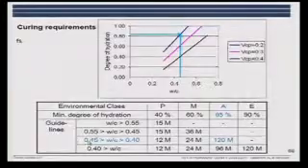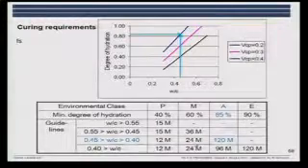And if we look at this table here and take an example where it's a concrete to go into an aggressive environment, and we have a water-cement ratio between 45 and 40. Take it here, move up, and have this 85. We see that it actually compares quite well with the 20% volume fraction of the capillary porosity, or 20% capillary porosity.